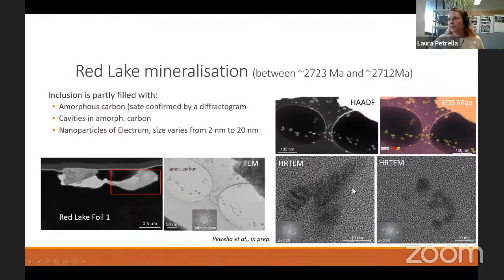These 2 images here are high-resolution TEM images of some of the nanoparticles. The nanoparticle size varies between 2 nanometers and 20 nanometers. And hopefully you might see on your screen some dark lines. These lines are lines of atoms, and we are able to measure the distances between the atoms, and the distance confirmed that these nanoparticles are indeed made of electrum.